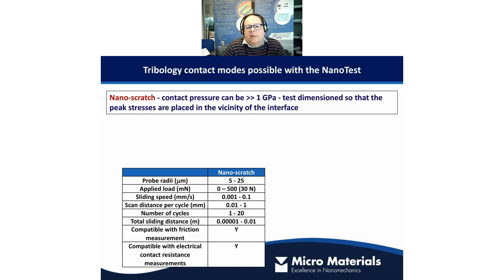Well, it's because they cover between them different types of contacts which can exist in the real world. So nano scratch testing, first of all, the contact pressures tend to be very high. If we're talking about a coated system, what we try to do is to dimensionalize the test. So that means to select an appropriate tip radius, probe radius, to get a maximum stress position somewhere close to the vicinity of the coating and the substrate interface.